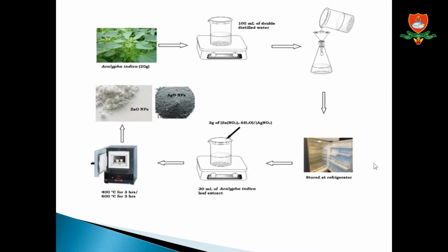The paste was transferred to a ceramic crucible and heated in a furnace at 400 degrees Celsius for 3 hours and 600 degrees Celsius for 3 hours.